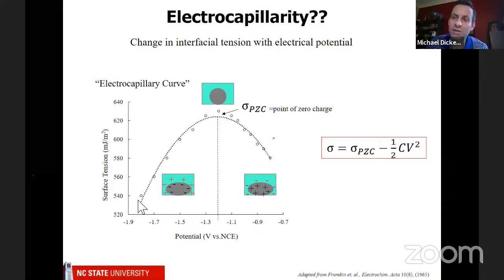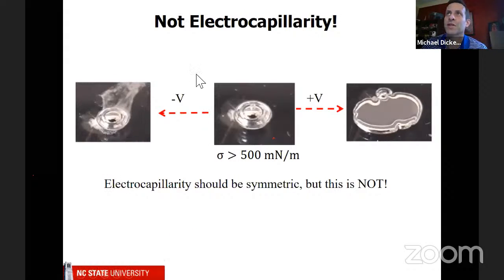So for a number of reasons, we don't think that this effect is electrocapillarity. I'm kind of sorry, because I just explained something that actually does not explain what we're seeing. But I needed to explain this, because what I'm showing you is different from over 150 years of science and theory. We think it's not electrocapillarity because in our case, when we apply negative voltage, the metal will bead up, and actually you can see hydrogen bubbles forming on the surface. And if we apply positive voltage, it starts to spread.